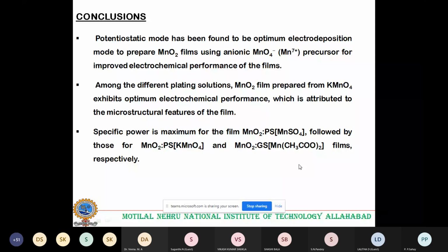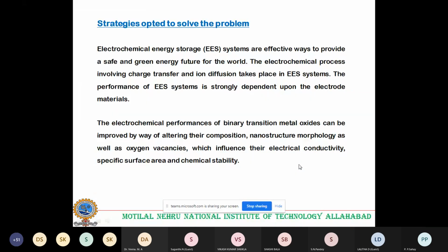The last few slides. So what is the problem with the transition metal oxide? The main problem is the conductivity of the film is not good. So you want to enhance the electrical conductivity. There are certain ways to do that, but not with independent oxides like manganese oxide. We have to use binary or ternary metal oxides. So that's why I mentioned the strategy opted to solve the problem.